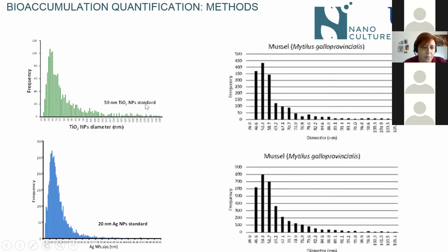Well, for the nanoparticles that we are using, you can see that this will be the spectrum of the size range that we will obtain with the nanoparticles. For the titanium dioxide nanoparticles of around 50 nanometers, we will obtain most part of the distribution of the size here, around 50, 60. And for the silver nanoparticles of around 20 nanometers, we will see here that the frequency of the sizes are mainly between 15 and 30.